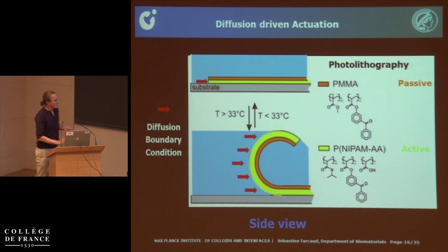So now let's come to the system we're studying. Leonid Ionov from Dresden came to us with this system. It's made by photolithography, and it's a thermoresponsive bilayer. So you have one passive layer on top, PMMA, that doesn't react to water, doesn't swell with water, even with changes of temperature. And on the bottom, you have another polymer, NIPAM, that actually swells about 10% when we switch above